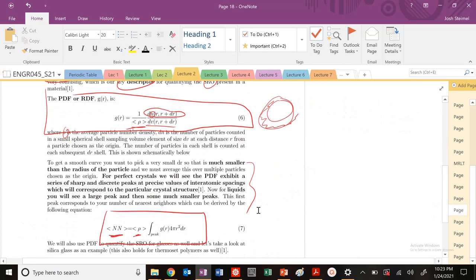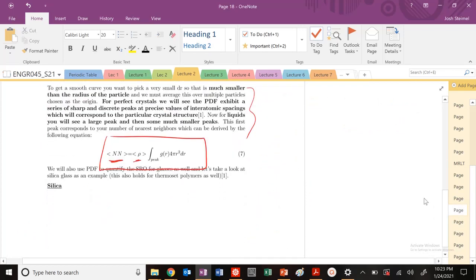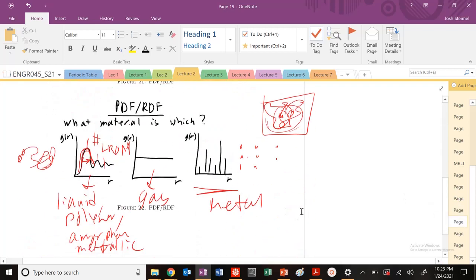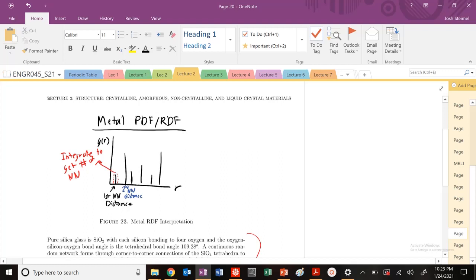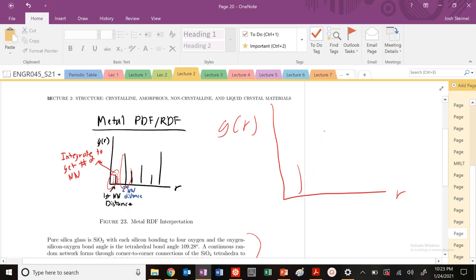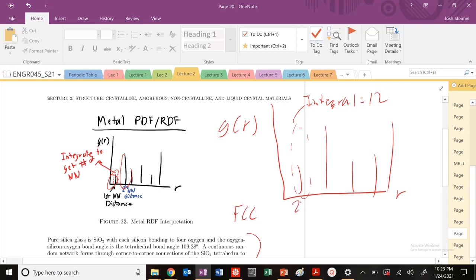So, you can start to imagine that I'm going to give you several problems where you're going to have to work with looking at these different metals and figuring out these values. So, remember, you can integrate this and get to those values. So, for example, for a metal, let's say I gave you a problem, like one in your problem set, perhaps. Let's say I said I integrated this peak, and I said that integral equals 12. Well, what structure, what cubic structure has 12 nearest neighbors? That's FCC. So, now I know that this first nearest neighbor distance is always 2R. I know the second nearest neighbor distance is 2√2R. So, if I gave you this value, I know these next, at least, if I know the integral, I now know what this position should be, and this position should be, the second peak should be, in terms of R. So, you could be given one of those values.